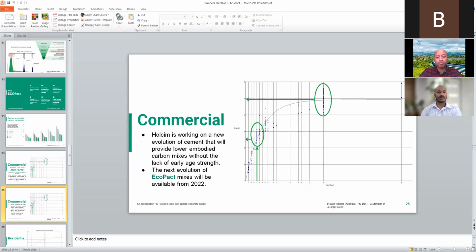This will enable us to achieve strength of 22 MPa and above as early as 2 or 3 days, whilst also reducing the embodied carbon by more than 35%. But I do warn you that this comes at a cost. So it all comes down to risk versus reward, as well as what we can achieve and what kind of sustainability targets we are aiming for at a project level.